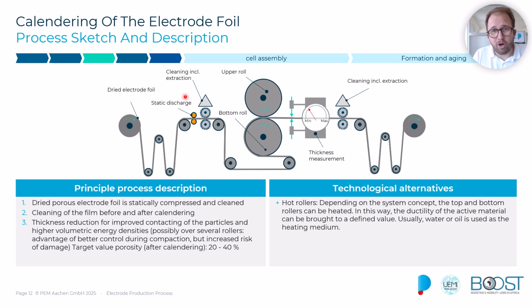And after calendering, normally you have also a cleaning process, making sure to take out all the particles which are maybe still there, and then roll up the coil again, preparing the electrode coil for the next production processes. So typically the line pressure defines the porosity of the coated material, and that influences ultimately, subsequently, the wetting properties, which become important in the electrode assembly, where you add the electrolytes. So with this, the energy density of the cell is highly impacted.